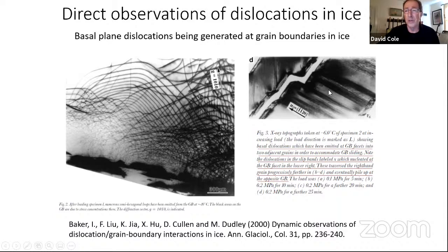Here's another image a little farther back. All these tangles of dark lines you see associated with the ledges along the grain boundary are in fact great numbers of dislocations being pumped out from the shear stress along this grain boundary. So again, there's really plenty of evidence of the existence, and in great numbers, of dislocations in ice. So it's basically a well-established phenomenon.